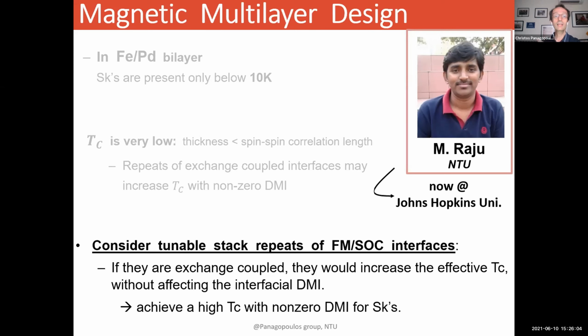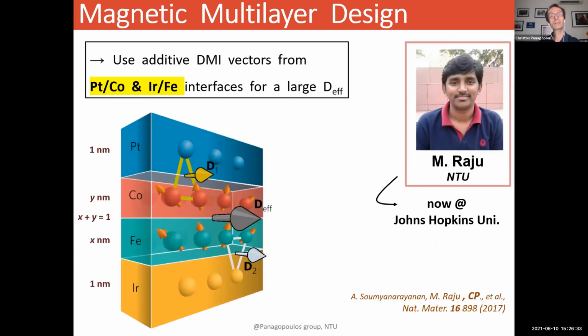So the idea is that if you exchange couple the ferromagnet and the spin-orbit coupling, that would increase the effective magnetic TC without affecting the interfacial Dzyaloshinskii-Moriya interaction. And you would achieve a high TC for your skyrmions and a non-zero Dzyaloshinskii-Moriya interaction. So in other words, you should be able not only to have these skyrmions at a wider temperature range, that is even up to room temperature, as we showed eventually, but also to tune their size and density by changing the stacks. And indeed, by having additive Dzyaloshinskii-Moriya interaction vectors from platinum, cobalt, and iridium iron, then you can actually